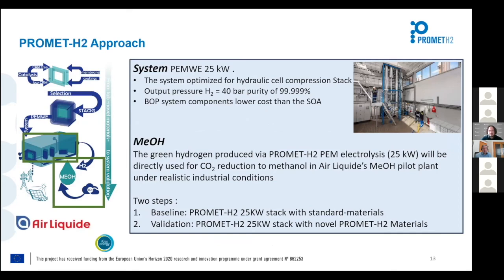Regarding the system, we wanted to have at the end of the project a stack of 25 kilowatts. Of course, to run the stack with hydraulic cell compression, we need a specific system. Our output pressure will be 40 bars in the project, with high purity of hydrogen. And also we claim that the balance of plant for the system components should be lower than the current state of the art. Regarding the methanol production, once we have this cheap green hydrogen, we will couple this with CO2 to produce the reduction, and then we will store it in the form of methanol.